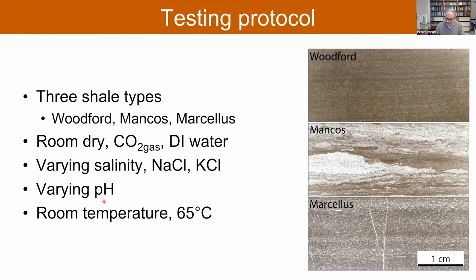Now we did this on 3 shales, and they are all commercially obtained, because core samples don't provide enough material, and outcrop samples are usually too weathered. So this comes from a quarry: a piece of Woodford, a piece of Mancos, and a piece of Marcellus. They were tested under room dry conditions, which has humidity, CO2 gas, which is very dry, DI water with nothing in it, or NaCl or KCl, and varying pH, at room temperature and 65 degrees.